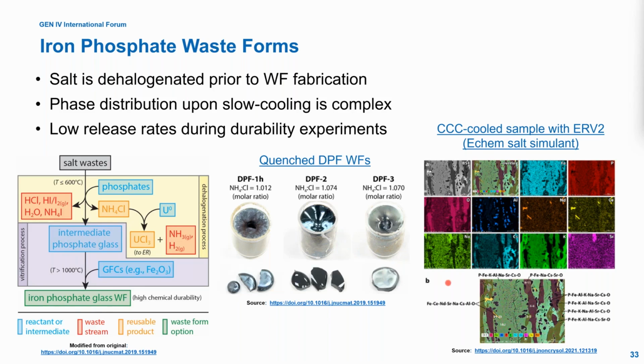One of the issues with phosphates is that they tend to create lots of different phases upon slow cooling. So if these were to be made at large scale, we would melt them in a melter and pour them into canisters. You can see here, this is a canister centerline cooled sample. This is an EDS dot map, but what I want to draw your attention to is the 7 different phases that are present here in the sample that are all very, very similar compositionally. So there's a lot of work that we're trying to do to understand the phase distribution as a function of cooling rate and initial sample composition. This is a complicated process that we're trying to understand better for this waste form.